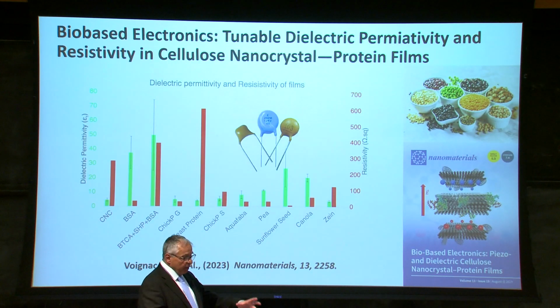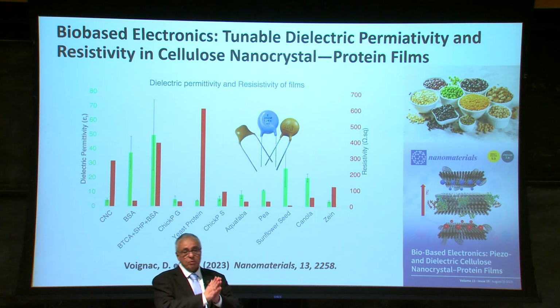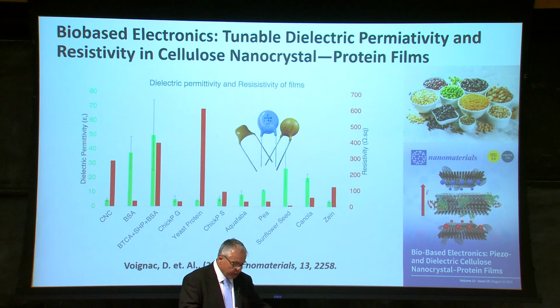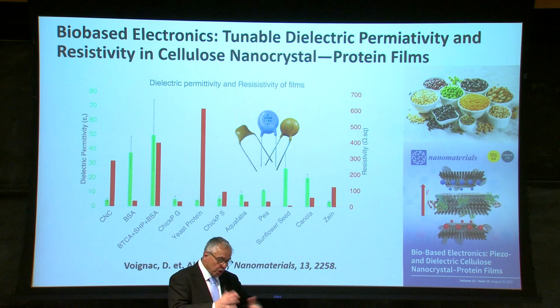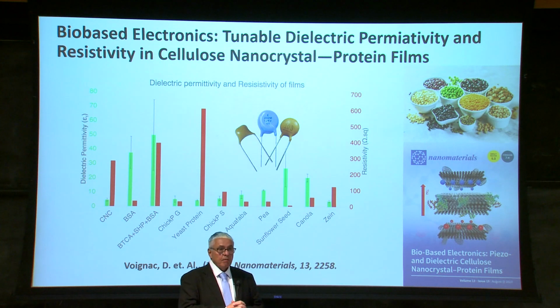But in order to do real electronics, we also need other devices like capacitors, for example. So we found out that if we take cellulose nanocrystals and you just mix them with different proteins, proteins that come from serum albumin, some that come from chickpea, yeast proteins, pea, whatever, canola proteins, we can really get tunable dielectric permittivity and resistivity and essentially make really good capacitors. The one that is actually winning here is the BSA. So now we can really start to realize bioelectronics, if you like.